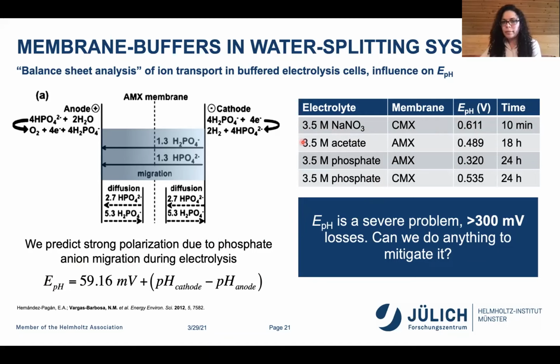If we look at a buffer like acetate, about 500 millivolt losses in 18 hours. And in the case of phosphate, we have anywhere between 300 and 500 millivolts of losses in about 24 hours. So this is a problem.